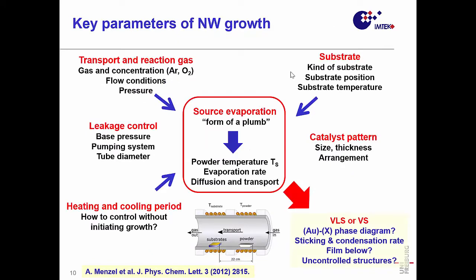So if you have such an oxide, which could be zinc oxide or in this case tin oxide, I'm going back to this image because I need the tube furnace down there. So what people are doing, because these oxides have a high melting point, and of course your quartz tube would not survive that, they're playing a trick. They're using zinc oxide powder and put a lot of carbon, that means graphite, in, and by doing that they are reducing the zinc oxide powder or the tin oxide powder to zinc gas and carbon oxide.